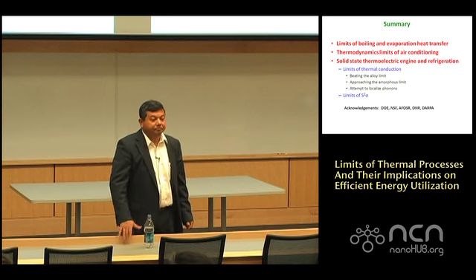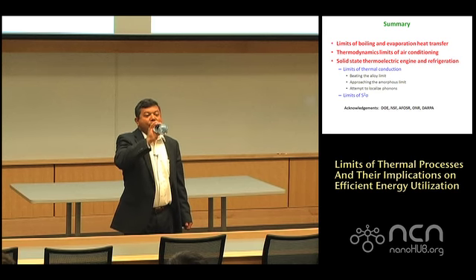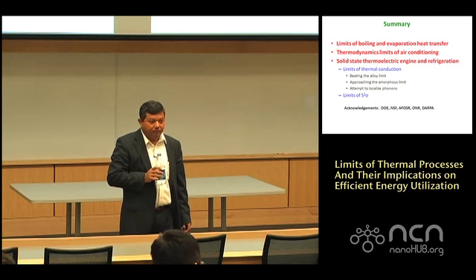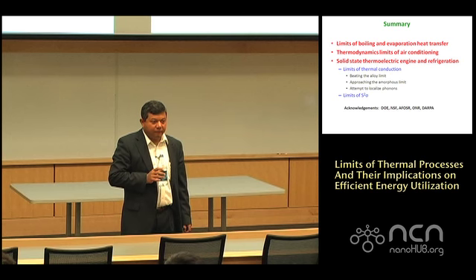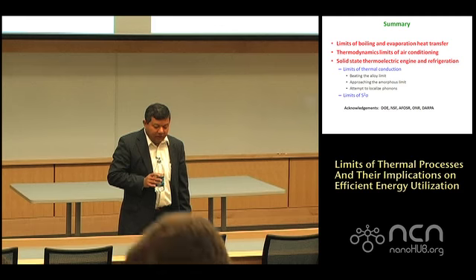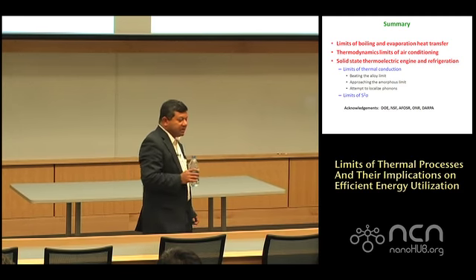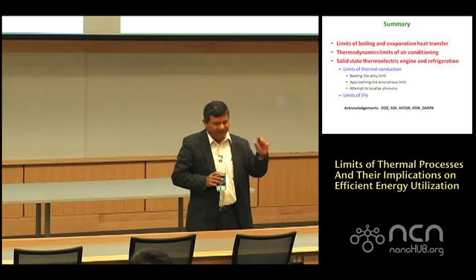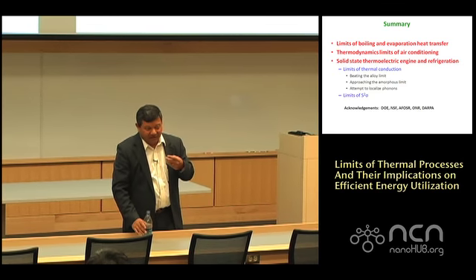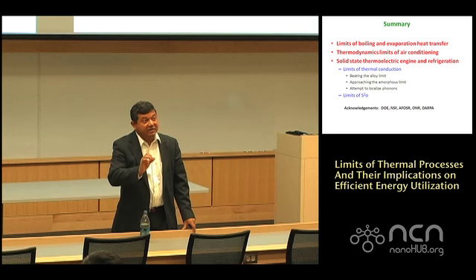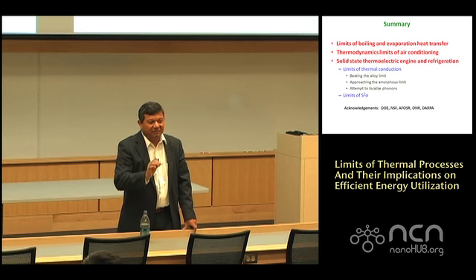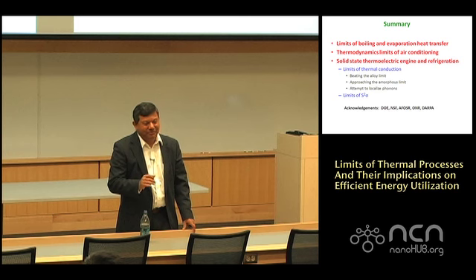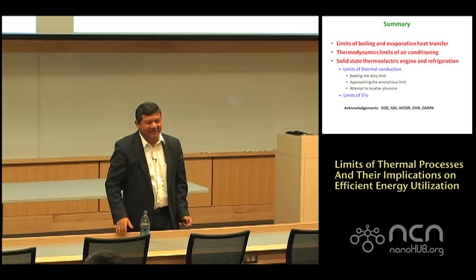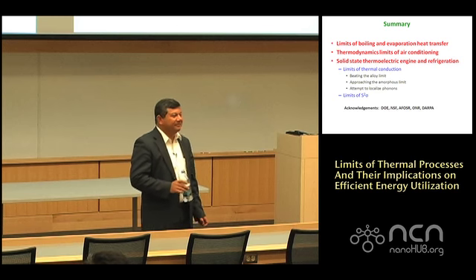Yep. So going back to the fact that even when the wires are monolithic, and you say that contact resistance better be zero, if we go back to basics, phonon transmission through apertures, aren't these wires already small enough that there's a contribution? Right. There's a Bethe scattering limit of size raised to 6, for any wave propagation through an aperture. These apertures are 40 nanometers now. It's not small enough. You have to get down to a few nanometers for those wires, which are really hard to make. So we're not at that limit yet.